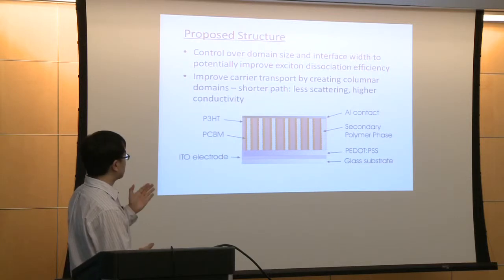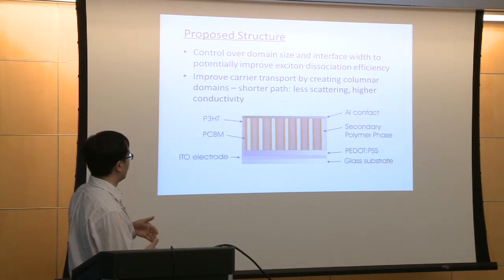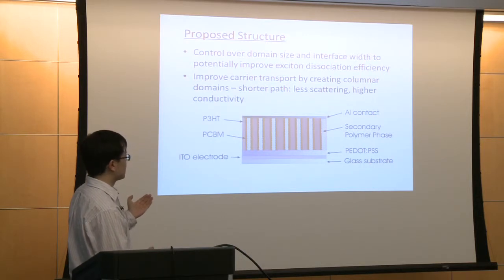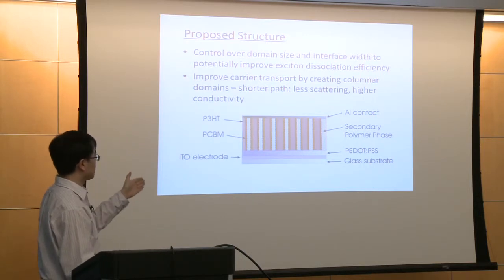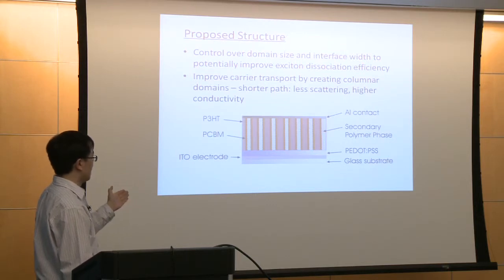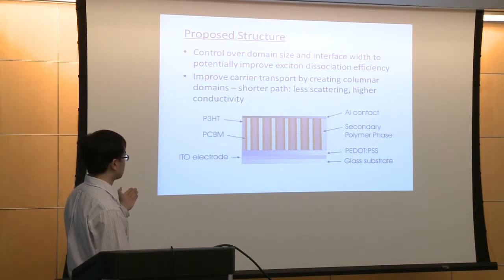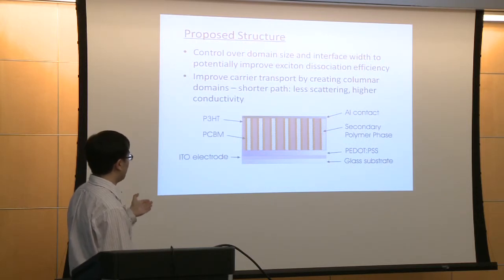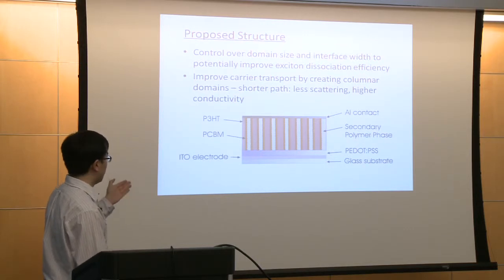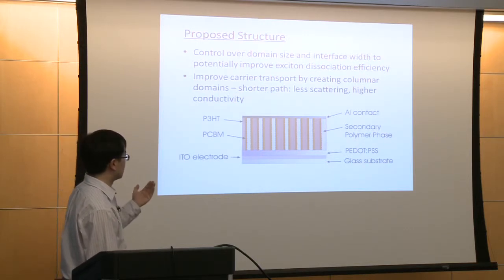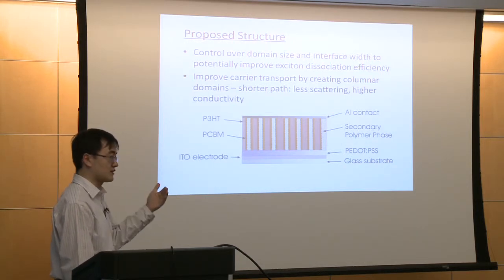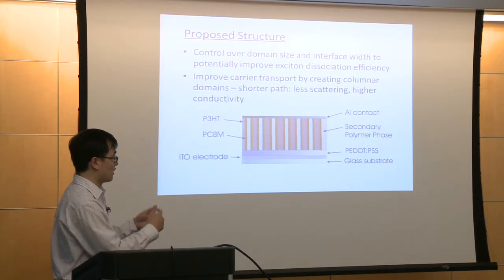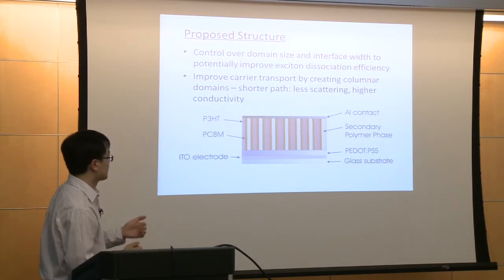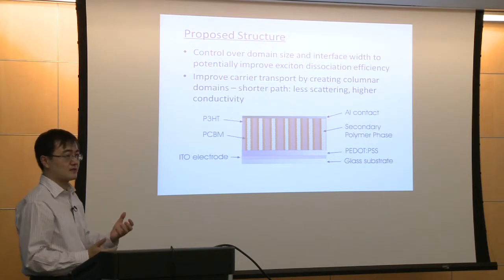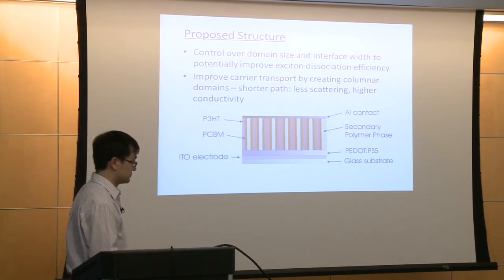So this structure, we think, can help to improve the exciton dissociation efficiency because the interface area is very large compared to the bulk heterojunction or the other kinds of solar cells. And also, when the PCBM are aligned along the interface between two polymers, the electrons can easily go to the electrode because there's a very straight way for the electrons to go. They don't need to walk around within the active layer. So the conduction path is greatly shortened with this structure.